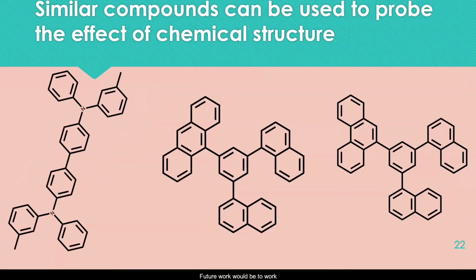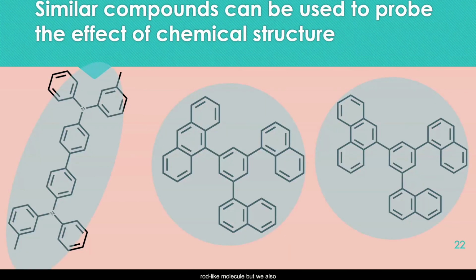Future work would be to work with similar compounds, which can be used to probe the effect of chemical structure. So I already showed you data from TPD, which is this long rod-like molecule, but we also have these more spherical molecules, which differ only by the addition of a single substituent. The anthracene substituent on the left is kind of bulky, while in phenanthrene, one of the phenyl groups is sort of bent out of the way. So that if I were to rotate around that single bond, it would be easier in the case of phenanthrene than it would be in the anthracene. This difference in rotational barrier is enough to change the packing of the system and therefore potentially the mechanics.